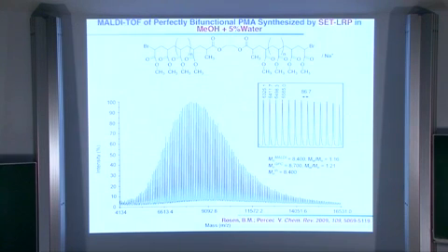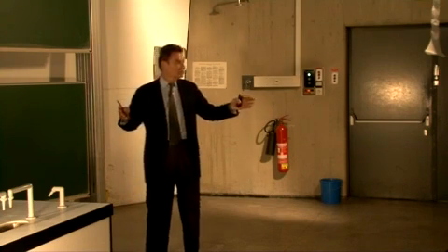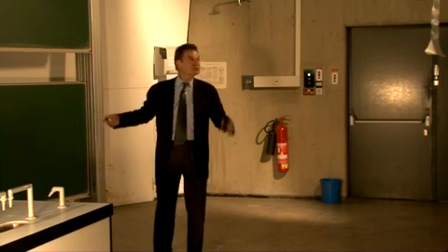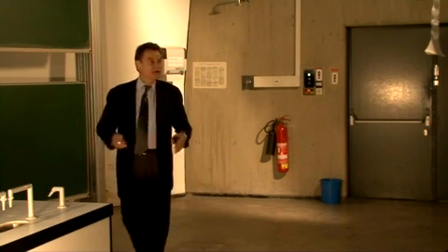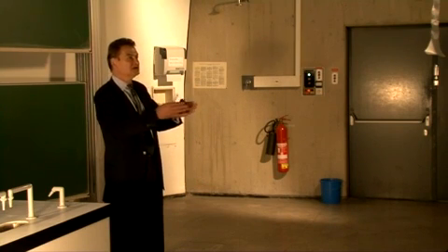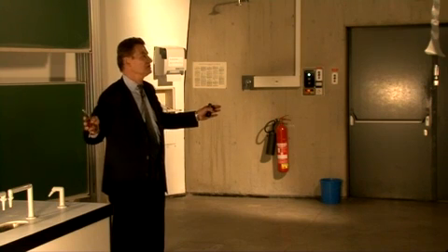There is no structural defect in the polymer, and it provides extremely narrow polydispersity, and an amplification of this MALDI-TOF is shown here. You don't see any second homologous species, but there is this number here that can be as low as 1.01. And that's the bad news of the entire story. A polymer that has a polydispersity of 1.01 is of no use for the rest of my lecture.